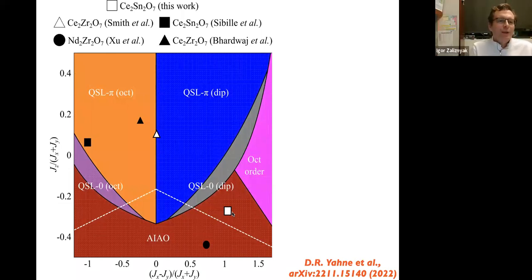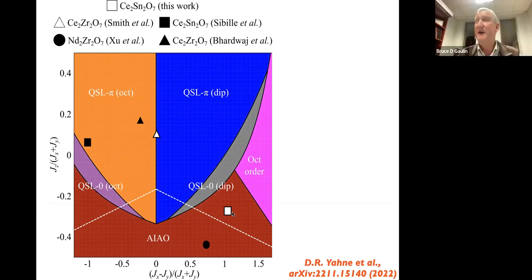Because the difference between 0.1 and 0.01 in terms of the GX to GZ ratio, the anisotropy of the G factor, makes a huge difference. In neutron scattering, 0.1 is visible, 0.01 is certainly outside, because the intensity that you measure is proportional to the G factor squared. Yeah, right.